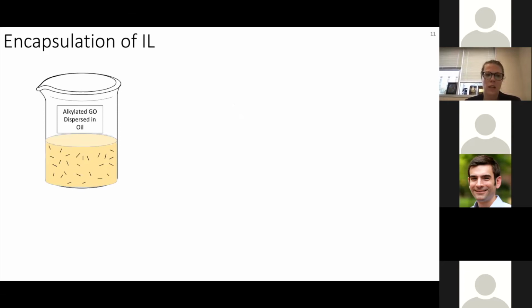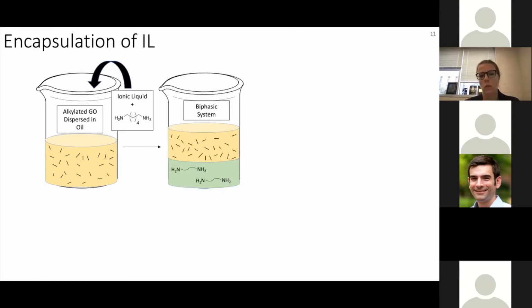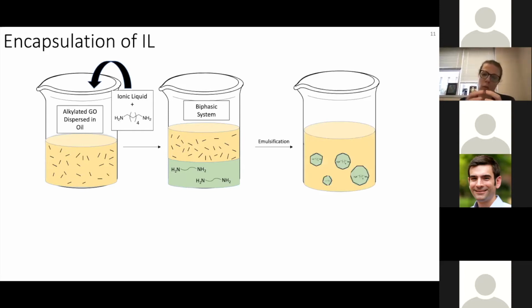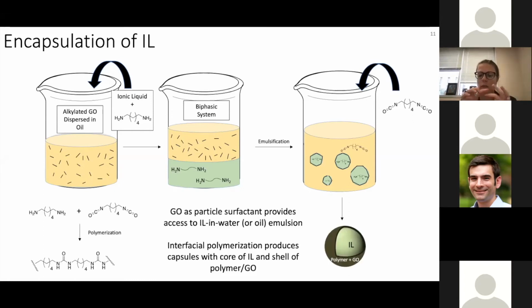compositions of ionic liquid. And so to make capsules in this case, so we can handle the liquid as a powder, we took the alkylated GO nanosheets in octane, added in the ionic liquid in which we had added a diamine. We get the biphasic system, and then we use a little handheld emulsifier to shear mix this and access droplets of the ionic liquid with the diamine in a continuous octane phase. We could then add in the diisocyanate, and we're relying on the reaction to take place at the interface here. So we actually have to leave these for a couple of days, and we get this polyurea formation around the nanosheets at the interface. So we choose the polyurea chemistry because the monomers are readily available.